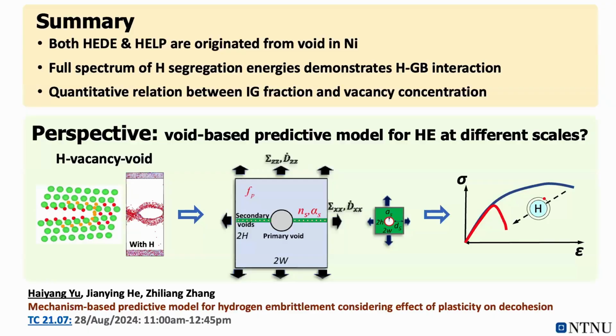Yeah, let's see the summary. What we can conclude from this work is that no matter which mechanism of hydrogen embrittlement, the damage in the nickel material always originates from vacancy and void formation. And this full spectrum of hydrogen segregation energy demonstrates the grain boundary interaction, and further demonstrates the vacancy concentration contribution to hydrogen embrittlement and induces this intergranular fracture in the nickel material.